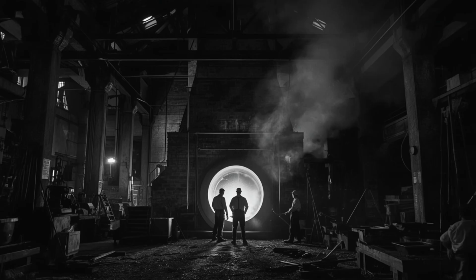Croft shares the data with Harding. Together they recognize something crucial. The vibration frequencies correspond to the acoustic tones everyone has been hearing. The deep hum from the left side is mechanical resonance in the lower registers. The higher roar from the right is turbulence-driven oscillation. The furnace isn't just burning asymmetrically, it's vibrating asymmetrically, locked into two distinct modes of acoustic behavior.